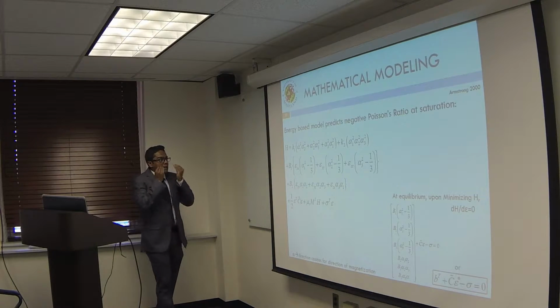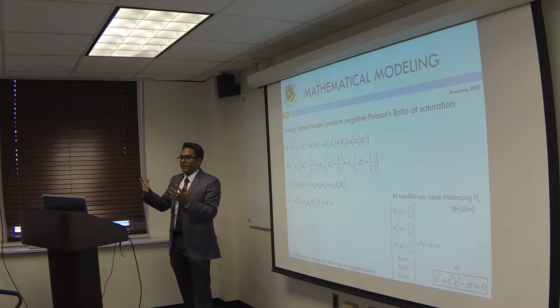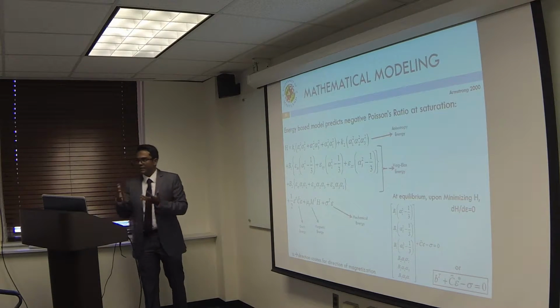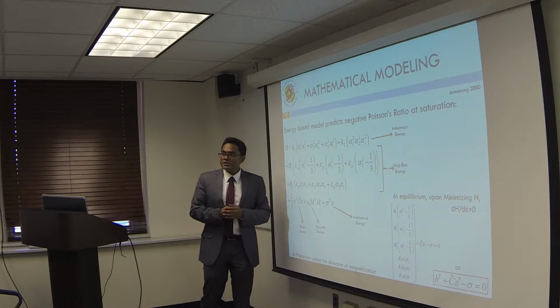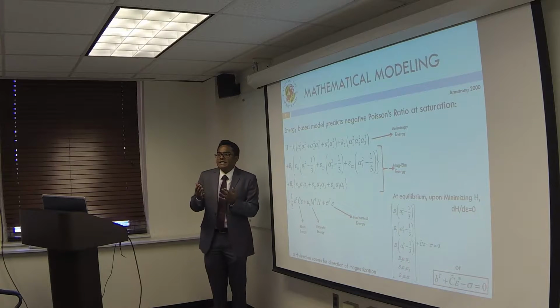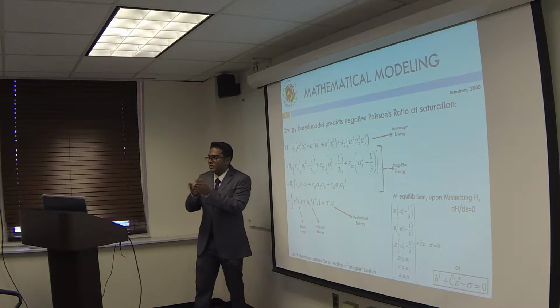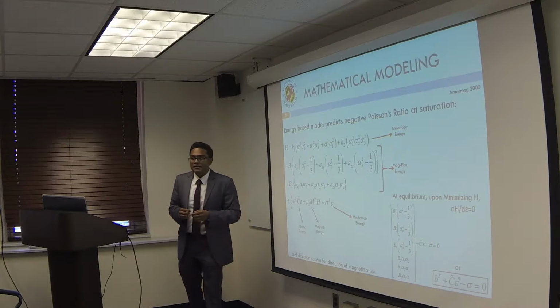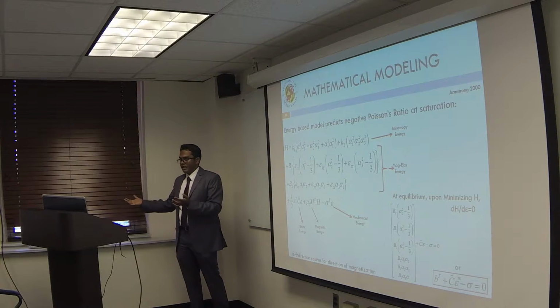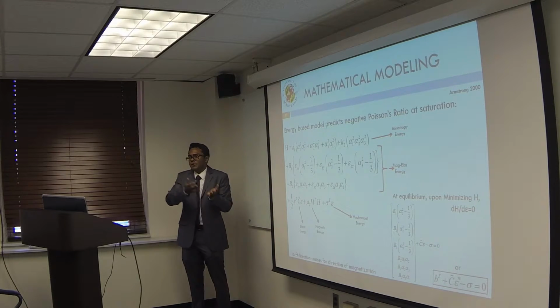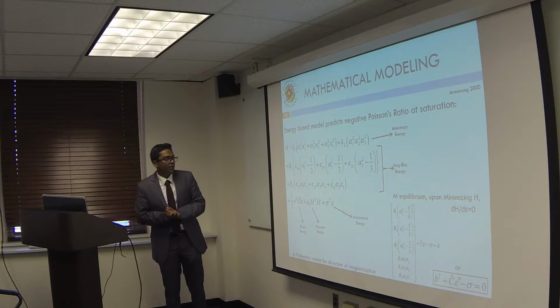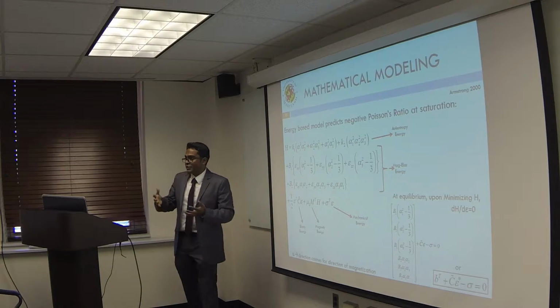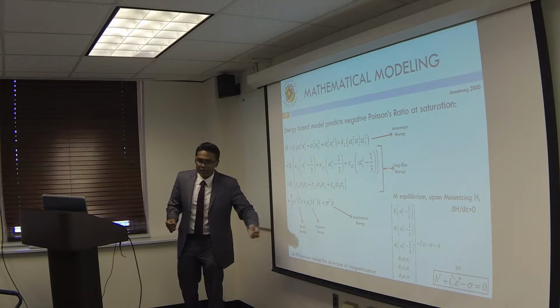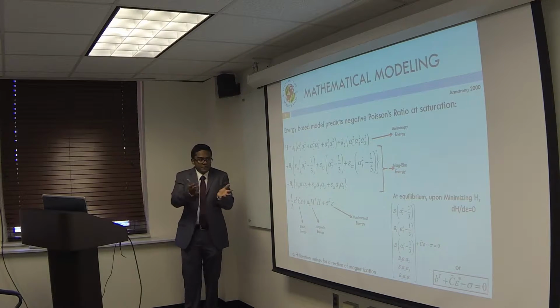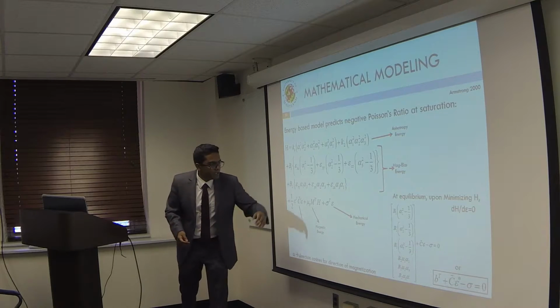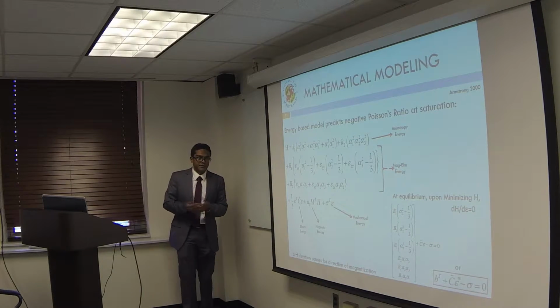Now let's jump into the mathematical model itself. So in any magnetoelastic system, there are 5 major energies that interact with one another. We have the anisotropy energy, and this defines how easy it is to magnetize along a particular crystallographic direction. We have the magnetoelastic energy, and this gives you a measure of how much magnetic energy you will get out of applying stresses and how much elastic energy you would get out of applying magnetic fields. And then you have the elastic energy by virtue of the stiffness present in the material. And you have the magnetic energy because you're changing the magnetic state of the material, and this gives rise to an increase in the magnetic energy. And finally, you have the mechanical energy, which is just a product of stress and strain.